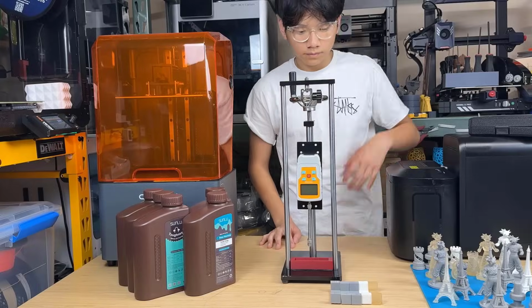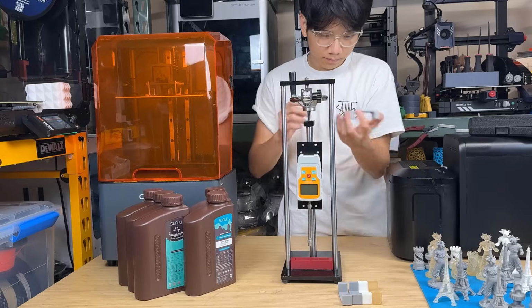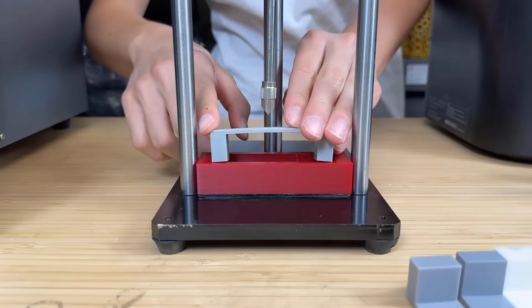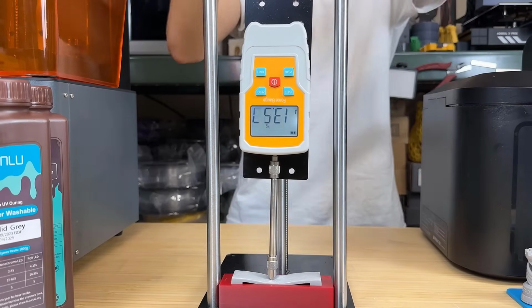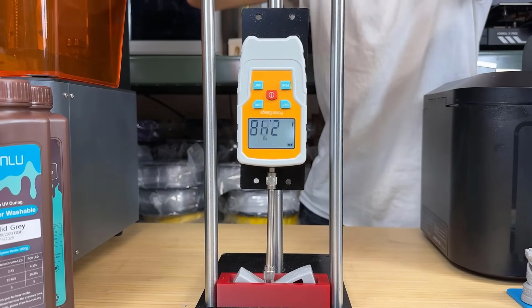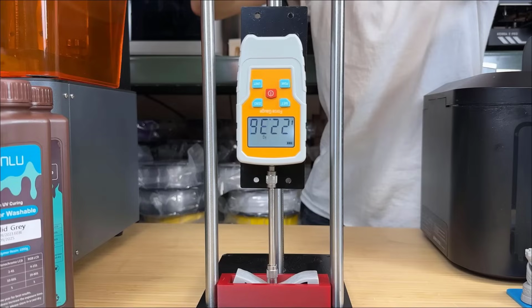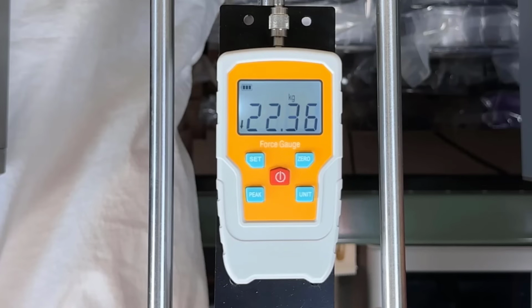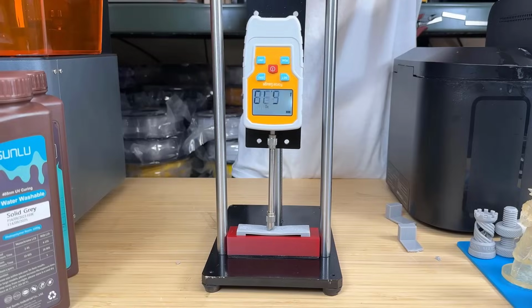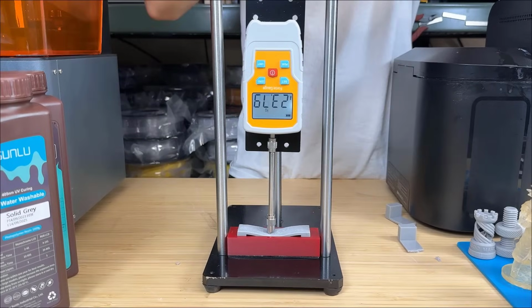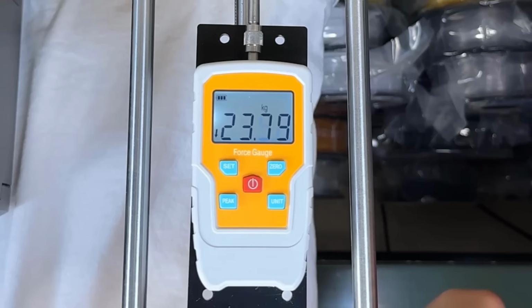I will now use a pressure gauge to test how much pressure is needed to break the resin. The thickness of the resin is 3 millimeters. Starting with the standard resin, the last frame before it breaks shows about 22.36 kilograms. Next, I will test a water-washable resin, which breaks at 23.79 kilograms, falling within the same range as a standard resin.